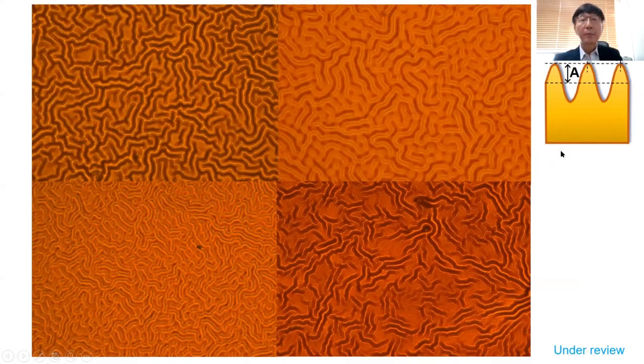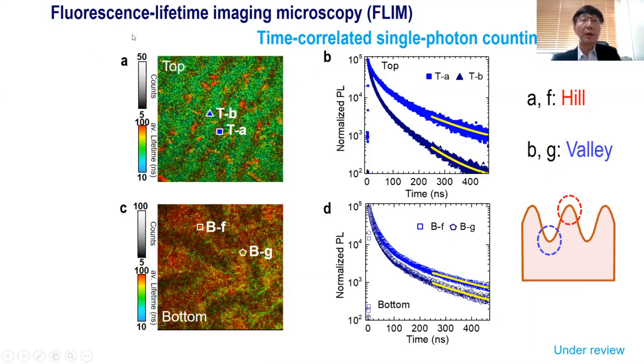So we can control various kinds of wrinkle morphology by tuning the amplitude and the wavelength of this wrinkle structure. Interestingly, we found from the fluorescence-lifetime imaging microscope combined with time-correlated single photon counting that A and F indicate the hill of the wrinkle structure, and B and G stand for the valley state of this wrinkle morphology. The hill state has a longer carrier lifetime than the valley state, which is very good, which means that the hill state has a highly crystalline structure. However, the valley state is a less crystalline state. So this is good for electron transport for the wrinkle morphology perovskite solar cell.